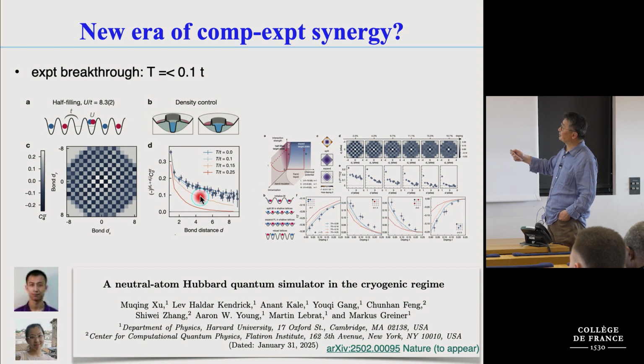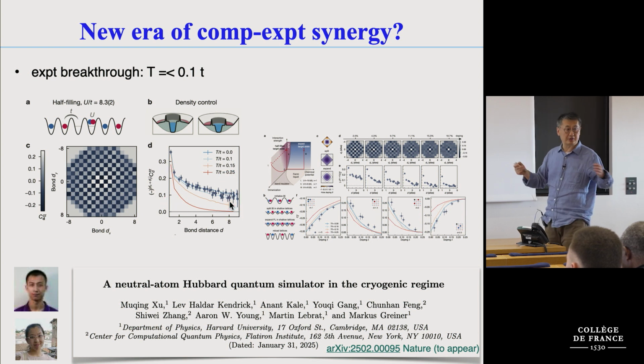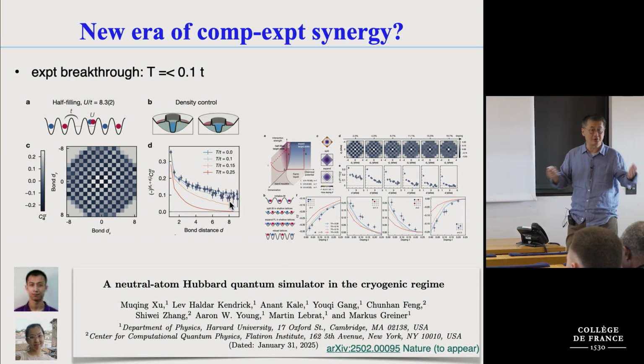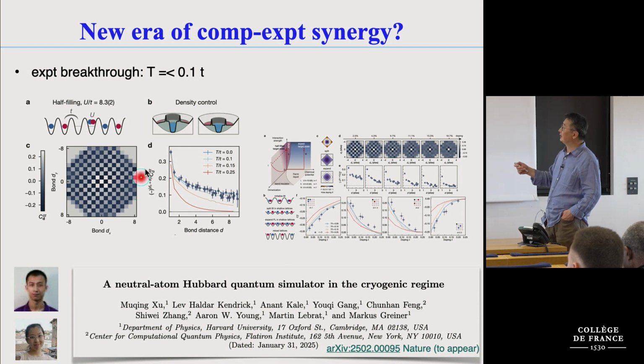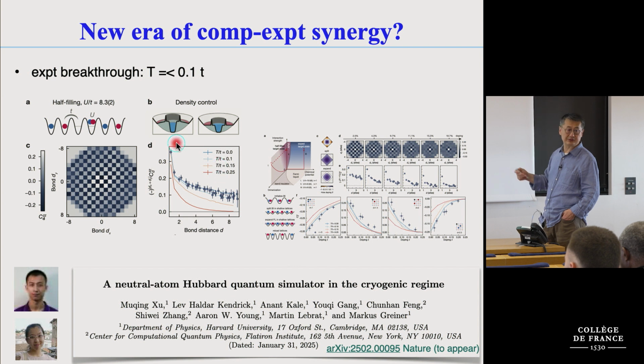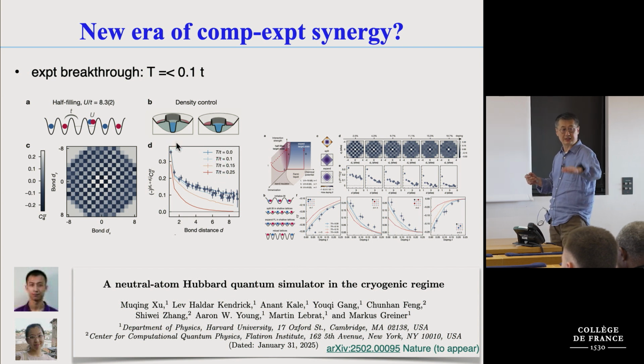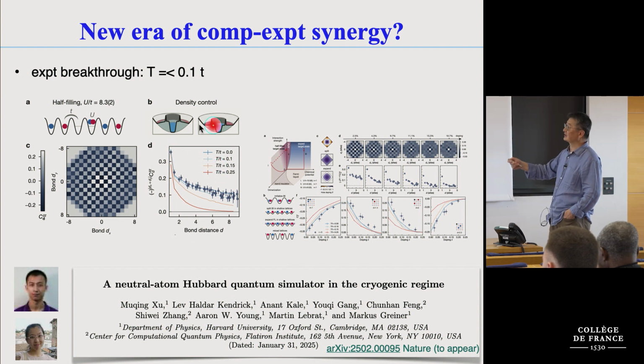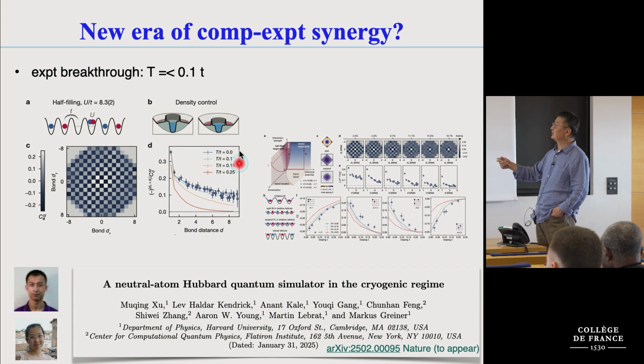But this is at different temperatures. It's our result, our calculation. So for example, 0.25 would be this red curve, which is where experiments were stuck at for a long time, about 0.25. And then this is 0.15 and 0.1, and ground state is this top one. You can see the data falls between about 0.1 and 0.0. So this is serving as thermometry, but the actual temperature is now below 0.1.